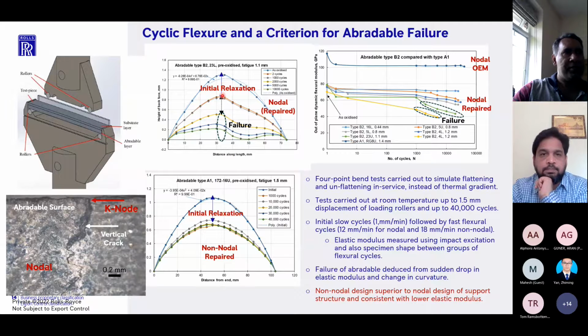after an initial relaxation that occurs because of the removal of residual stresses, if you look at the non-nodal design where you do not have any K nodes and X nodes, you do not see any more change in shape, even though the number of cycles goes from 10,000 to about 40,000. But on the other hand, in the case of the nodal design, where cracking is occurring at the nodes, the K and the X nodes, you see a gradual flattening or permanent deformation of the abradable.